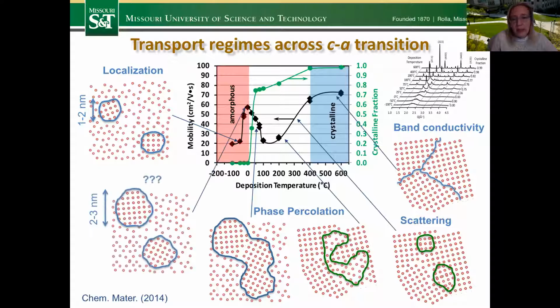However, if you look at the nanostructure, and these are cartoons, of course, but what has been observed from the TEM resolutions, for example, high resolution approaches, is that we still have some nanocrystallites inside this material. Those nanocrystallites, however, just decrease linearly, so they are unable to explain the mobility peak. So the black curve that I'm showing here is the electron mobility, and as you can see, the mobility goes down as we go from the band conductivity, just simple scattering on the grain boundaries, ionized scattering.